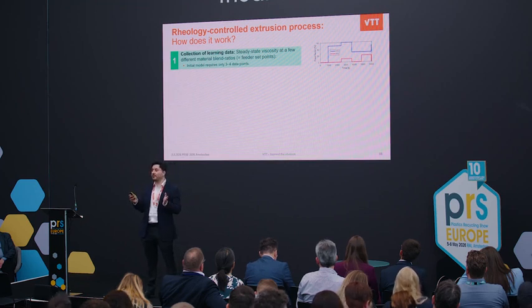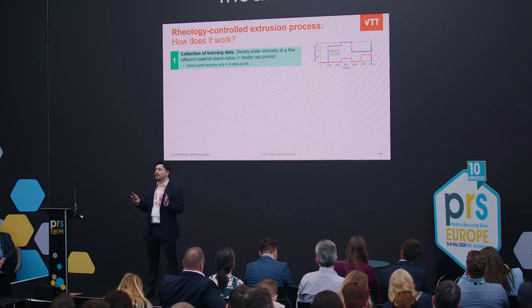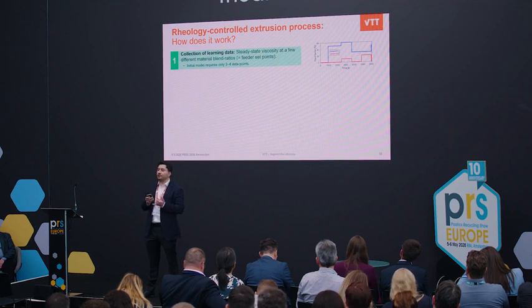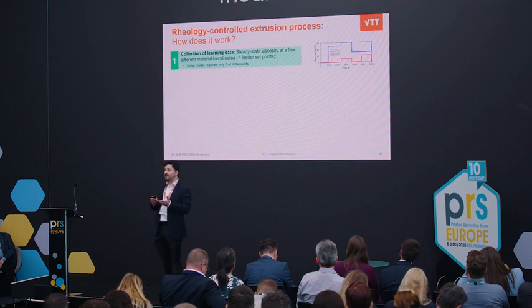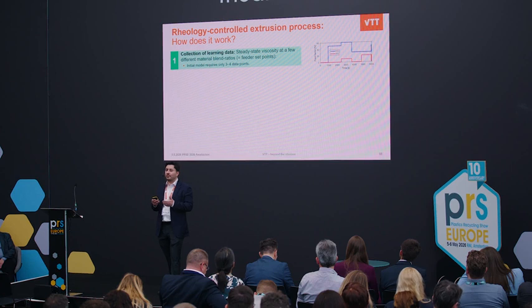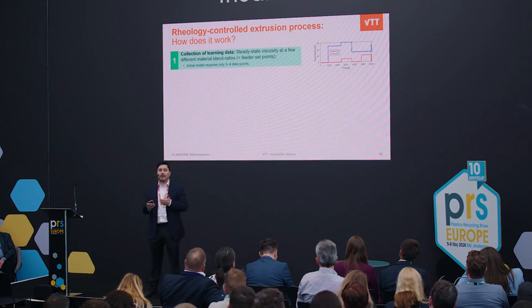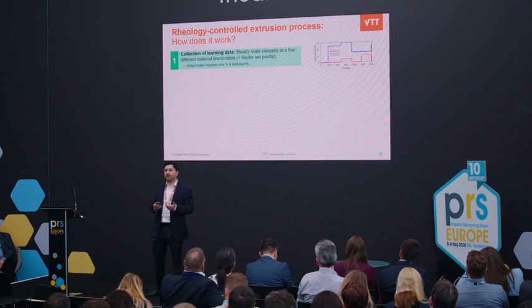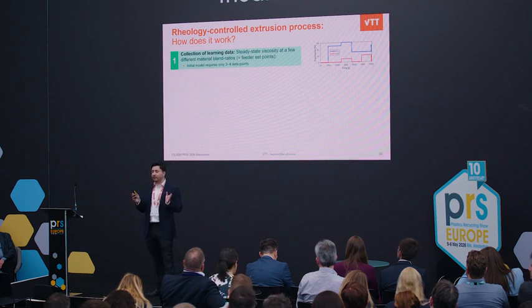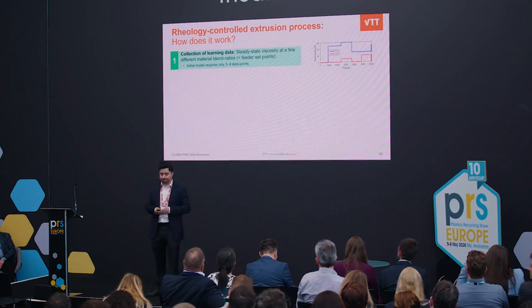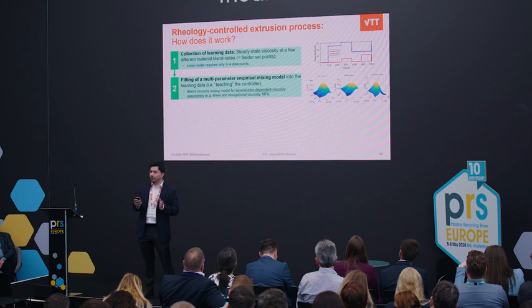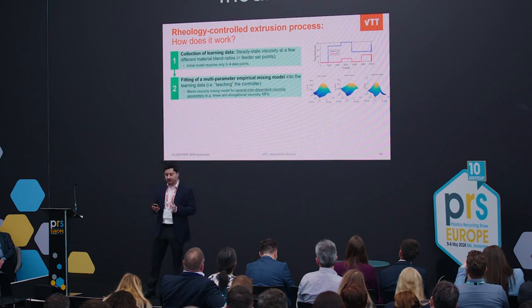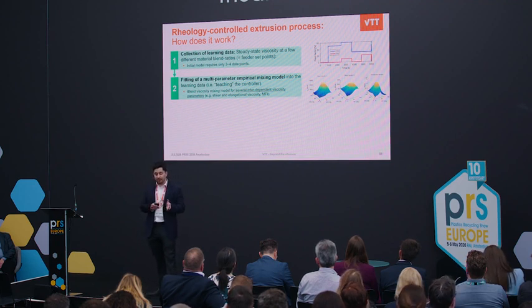So the equipment is taught with virgin and waste feedstock blends. You can, for example, have 80-20 virgin waste feedstock ratios, and then you have 60-40, 50-50, 30-70, and the equipment gathers all the data. And all of this data is fit into a multi-material empirical mixing model.